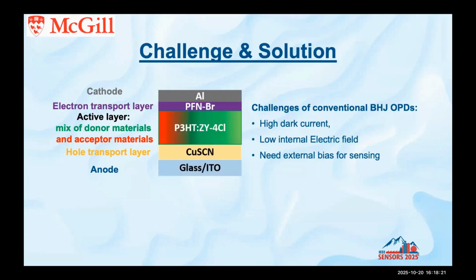The challenge that we have for the conventional bulk heterojunction OPDs, or organic photodetectors, is that I can start with a device of a photodiode. OPDs have one anode material, normally ITO. Then we need to have a hole transport layer, and the active layer, or the layer that absorbs light, includes a mixture of donor materials and acceptor materials. On top of that layer, we have an electron transport layer, which could be thermally deposited or spin coated. And then we need another layer of metal cathode with a different work function over the anode. This is the conventional bulk heterojunction structure.